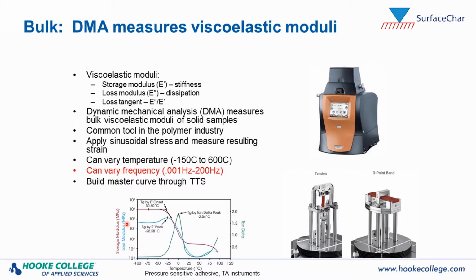So this is showing the storage modulus in red. In blue is the loss modulus, and then the green is the loss tangent, which is the ratio of the two, for a pressure-sensitive adhesive. And all these moduli are measured as a function of temperature, where this peak in the loss tangent is very instructive because in general these peaks can pinpoint thermal and structural transitions in the material.